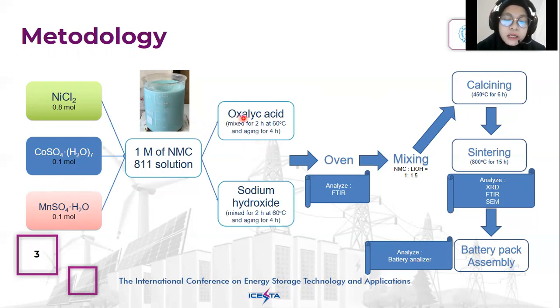The precursor of NMC oxalate was prepared by mixing NMC 811 solution with oxalic acid as the precipitating agent and ammonium bicarbonate as the chelating agent, mixed for 2 hours at 60 degrees Celsius and 4 hours for aging. While NMC hydroxide was prepared by mixing sodium hydroxide as the precipitating agent and ammonia as the chelating agent in the same condition as NMC oxalate. Then the solution was dried in the oven, and after that, the FTIR analysis was carried out.